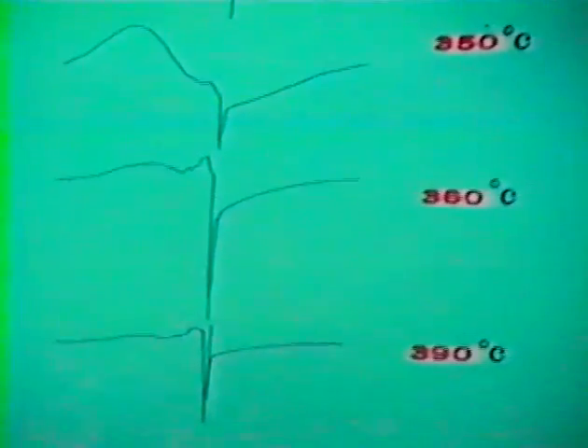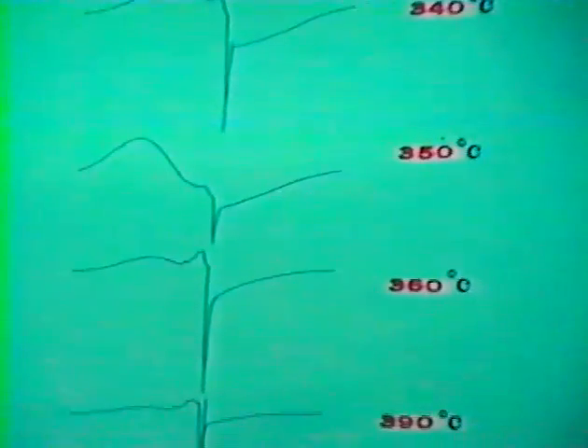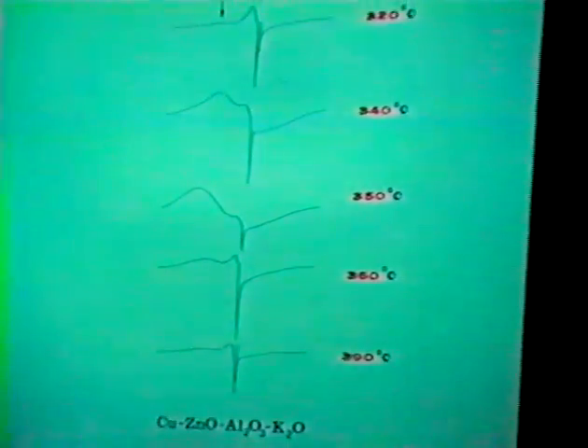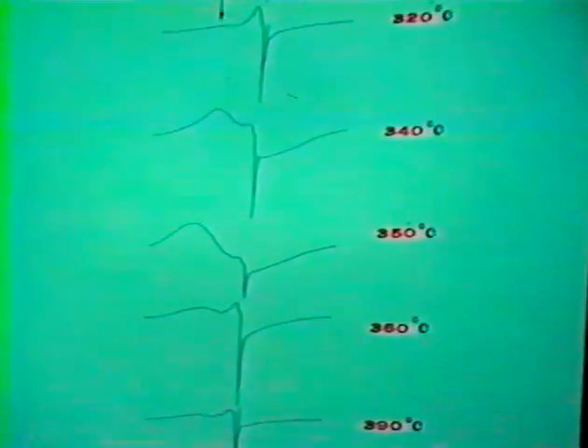Above 350 degrees, it will gradually increase again. But the signal C first grows and increases until the signal A appears, then it decreases, and above 350 degrees, when the signal A decreases, the signal C increases again. So what happens there? Let's go to see the signal B first.